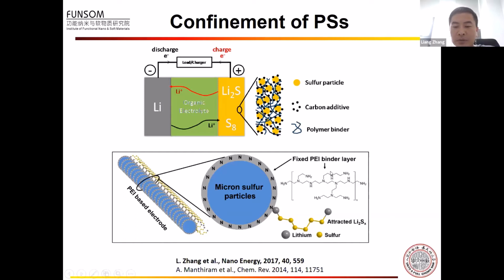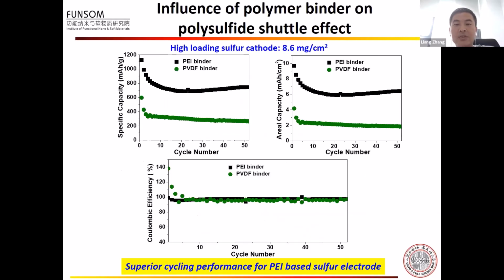So here we propose to use polyethylenimine, PEI for short, as the polymer binder. The advantage of the PEI binder is it has abundant nitrogen-containing functional groups. It also has a branched structure, which can provide a very strong affinity to the polysulfide. So this is the cycling performance for the PEI binder. We compare with the commercial PVDF binder. We can clearly see the cycling performance is greatly improved by using the PEI binder.